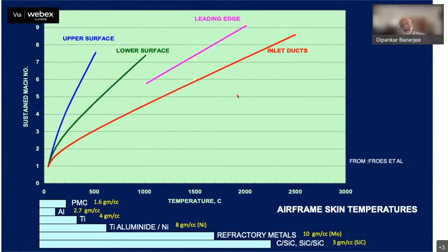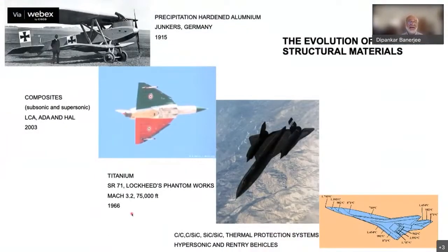And so if you look at airframes, typically the material that you use in airframes depends on the sustained Mach number of the vehicle that you're applying the material in. Therefore, for high subsonic and low supersonic flight, you're happy to use polymer matrix composites or aluminum because the skin heating due to that Mach number is limited to about 150 degrees centigrade. As you increase the Mach numbers, the skin heating becomes higher and higher, leading to higher airframe skin temperatures, and you have to graduate to different kinds of materials. And this therefore fundamentally determines the kind of materials that you use in an airframe.